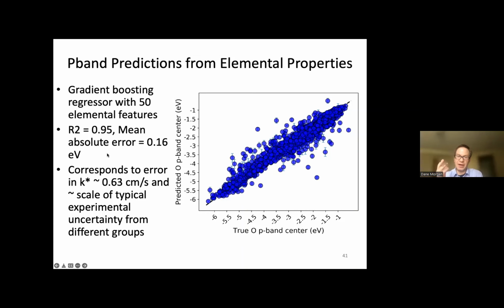We had a typical error of about 160 milli-electron volts in the p-band. You can see it ranges over almost 6 electron volts. That's a pretty small fraction of the error. And this is actually what's called a parity plot. It shows our predicted p-band centers as a function of the true p-band centers using machine learning. Now, by true, I mean DFT calculated, and by predicted, I mean using machine learning. So the fact that they fall almost on the identity line with a certain modest spread tells us that we can actually do a pretty good job of predicting p-band centers just from knowing the elements that are involved.